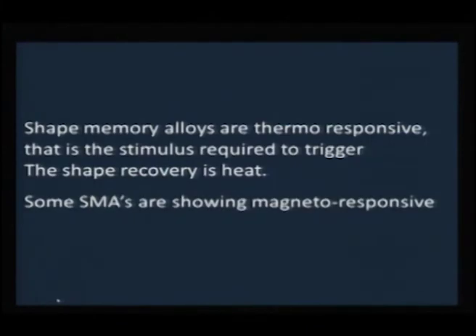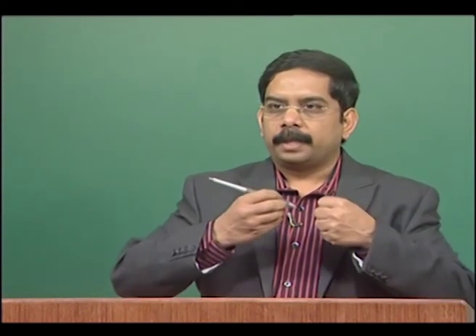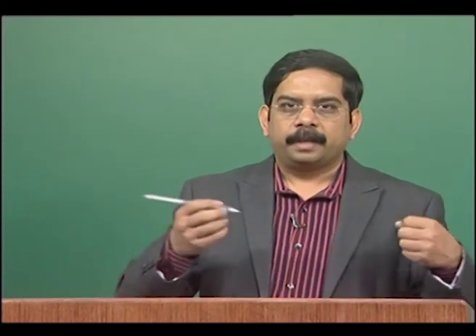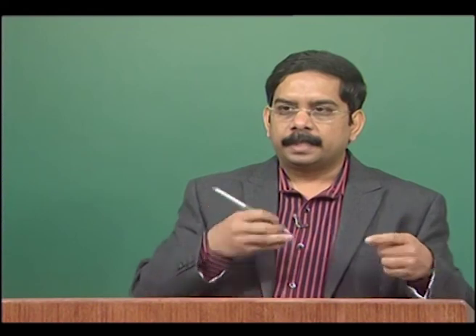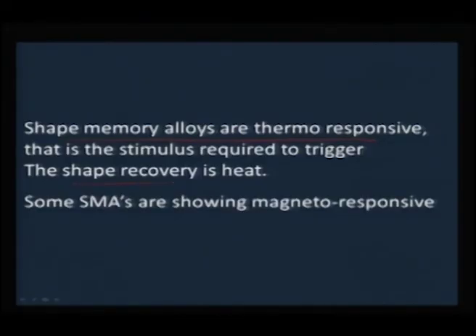As I told you in the beginning, shape memory alloys are thermoresponsive. So, at low temperature, suppose you try to make a particular shape like a spring or a hook using the alloy, then at a high temperature you can actually remove that shape, at the transition temperature or the temperature where there is a martensitic transformation of this alloy, and once you cool it down, again the same shape that you formed for this alloy can be retained. So, this is called thermoresponsive. The shape recovery is by heat. Some shape memory alloys also show magneto response. In other words, by applying a field, you can revert it back to the same shape.